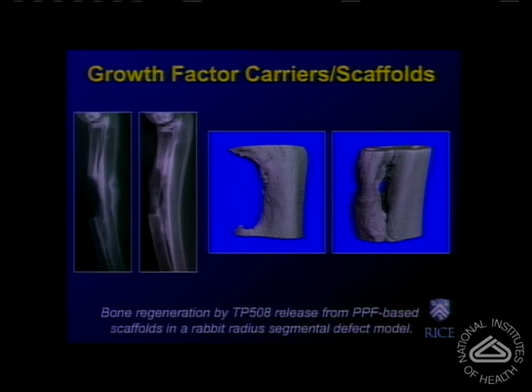This is a slide from a study that involved the controlled release of an osteogenic peptide, a 23 amino acid peptide that was isolated from thrombin, in a non-healing defect in the radius of a rabbit. So here we have the defect in the radius, and different scaffolds releasing different doses and different release kinetics of these bioactive molecules were tested. And what we found was that we had union and formation of new bone tissue only when we delivered this bioactive molecule to be released in an immediate fashion. So only when the bioactive molecule was released immediately, that was to our huge surprise.